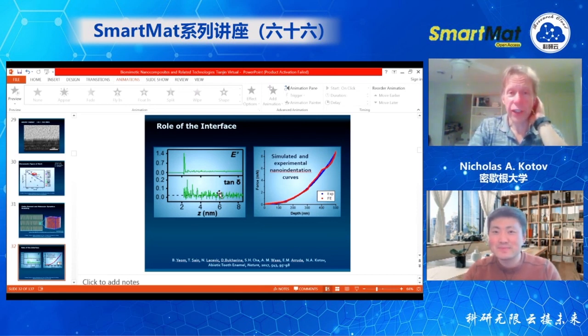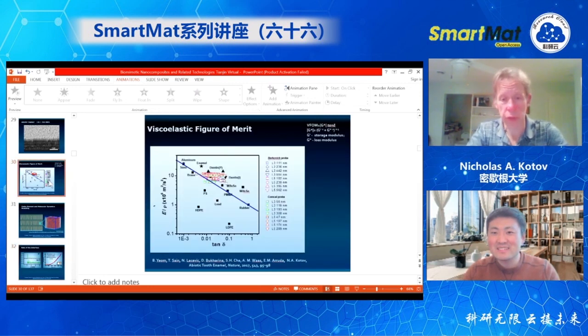And the longevity of these organs is critical. So it's not necessarily how super stiff they are, but actually how long they last overall. And that requires damping the vibrations because they create microcracks. So the longevity is a result of the combination of high stiffness and viscoelasticity, and the viscoelastic properties, the damping coefficient tan delta, as we can see on this plot. Hope I answered your question.